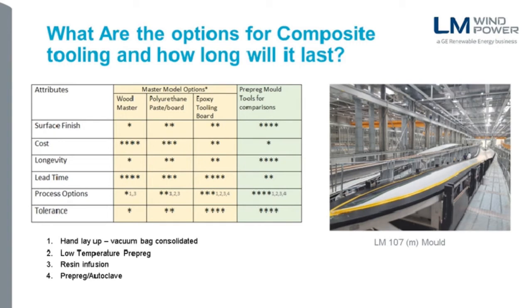So if it's prototyping, testing and trialing, master models, direct molds using CNC, epoxy tooling board is great, but don't expect more than 10 or 12 parts before the tools start to deteriorate. Then the cost is worth investing in composite tooling, bespoke and specific for the component and the process and the cure temperature, because that should run up to 1,000 or 2,000 or 3,000 components before it needs renovating or properly being repaired. So that's quite a nice indication of what is the best tool.